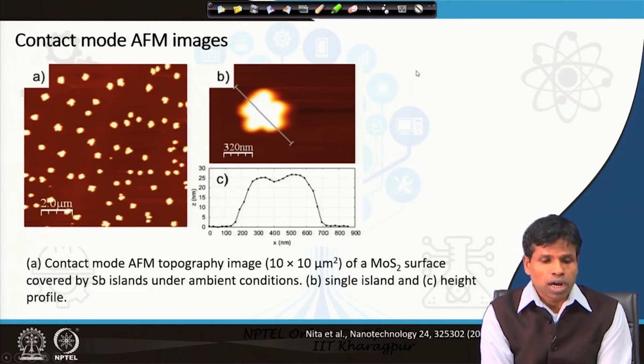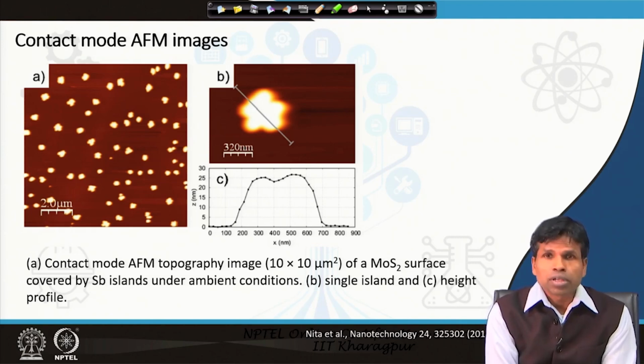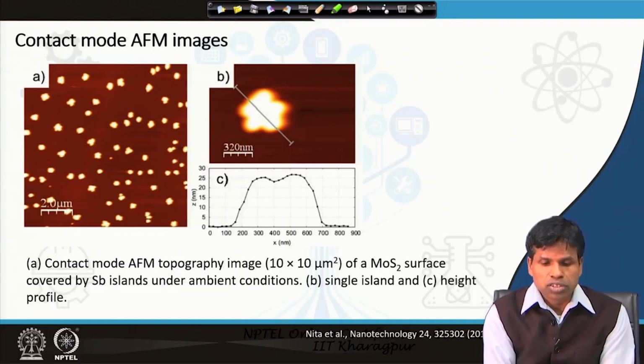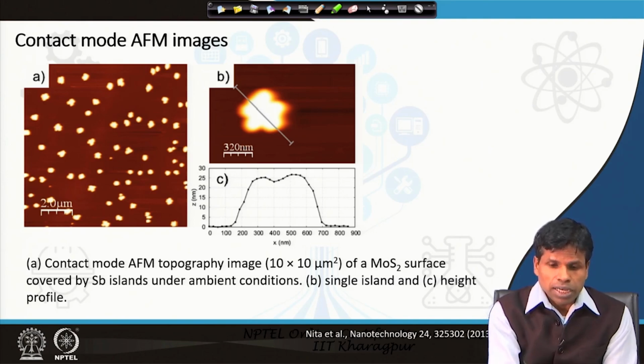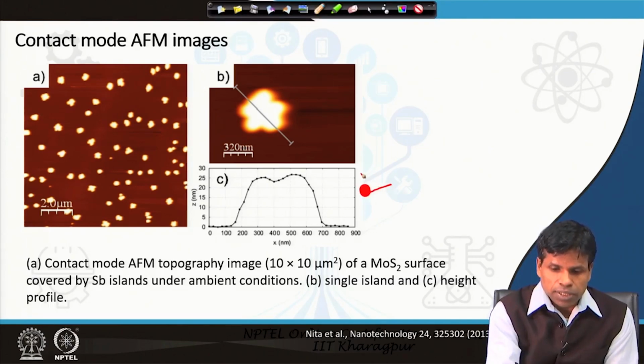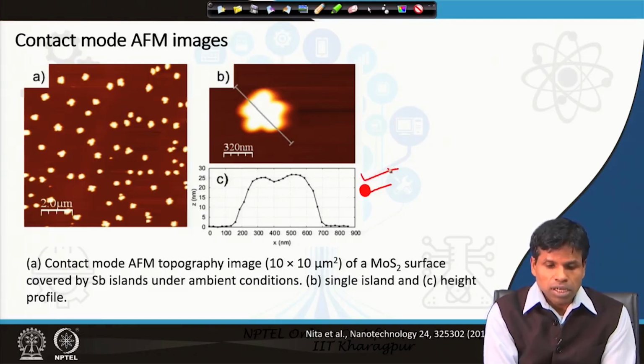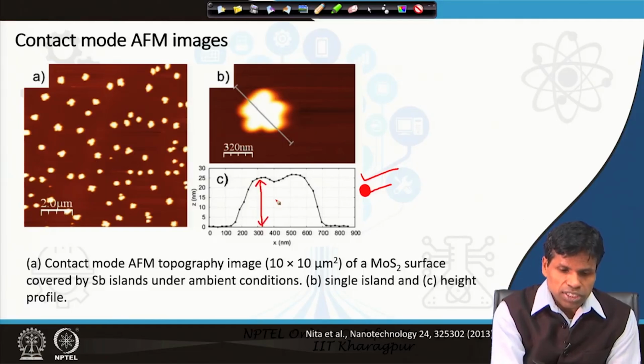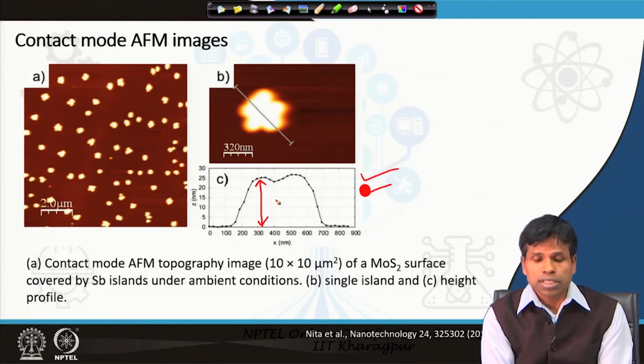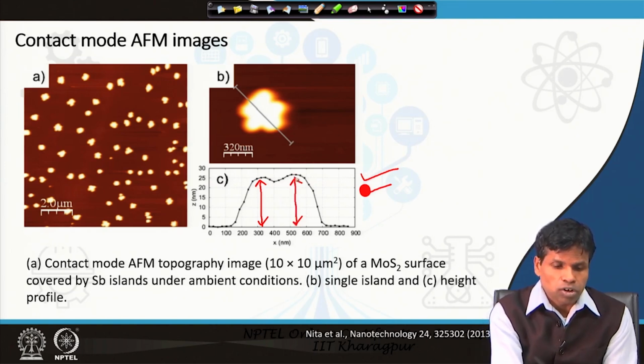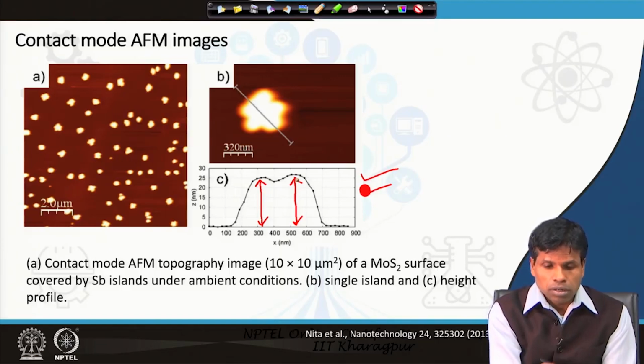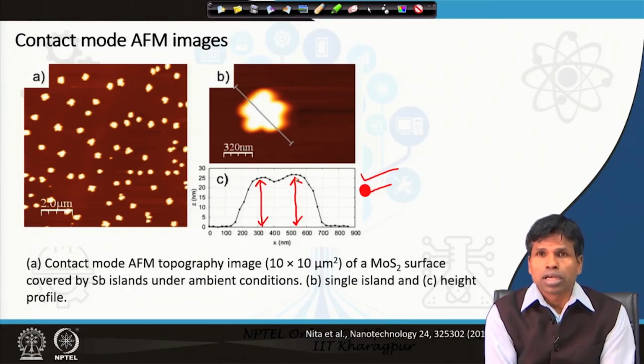Here is another example of how this contact mode helps in measuring step heights. These are clusters of antimony particles on the MoS2 surface in the left side image, and in the B image you see a single zoomed-up cluster, and in the C you see the height versus distance curve, the Z curve, telling about the height of these clusters, which is approximately 25 nanometers in this case, accurately providing the height of these clusters on the surface, which cannot be measured by other microscopic techniques, including optical and electron microscopic techniques.